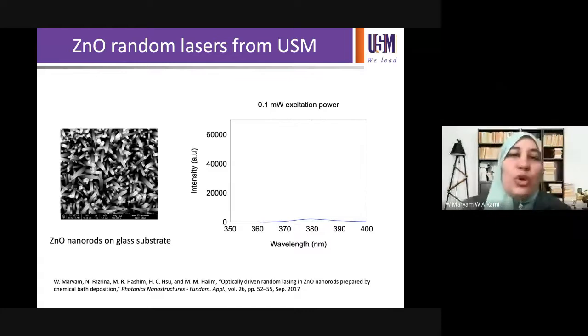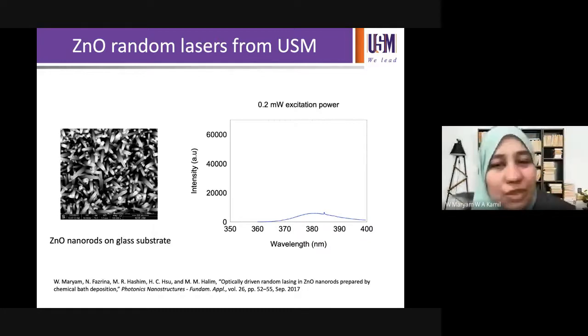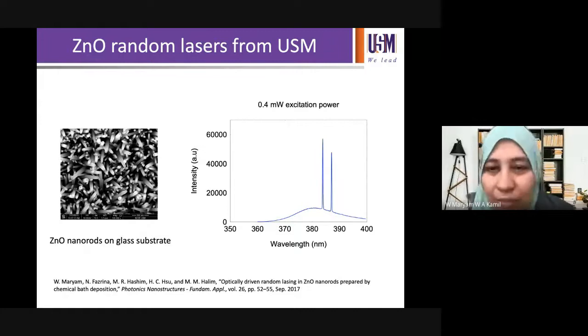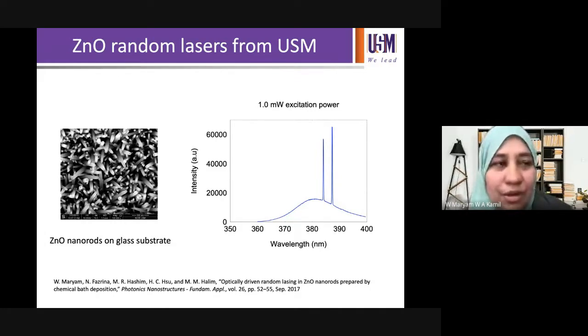But what we realize is that as we increase the excitation power, the pump power, we start to see a peak. So lasing is starting to occur. And as we increase that pump power, yes, we see the modes coming. So 2 modes were observed for this particular sample. One mode is more superior than the other, but as you increase the power, this mode increases the intensity even more. But then there is a fighting of modes. There are times when this mode dominates, there are times when the other mode dominates, and this happens all the way until whatever high power that you go to. Okay, so what we observe is that there is a fighting of modes.